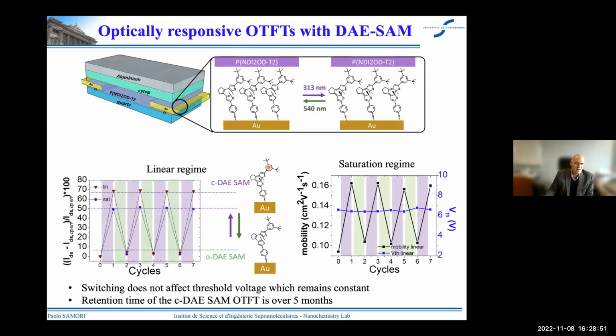Now let's integrate this inside the real device, and you can see, both in the linear and saturation regime, that we can change the current through the junction. This can be read also in terms of change of the mobility through the junction in a highly reversible manner with very little fatigue. The threshold voltage doesn't change, so we are not really doping our system. And what I'd like to stress is that thanks to the thermal bistability of the diarylethene in the two states, we have a retention time of the closed diarylethene that is exceeding 5 months.